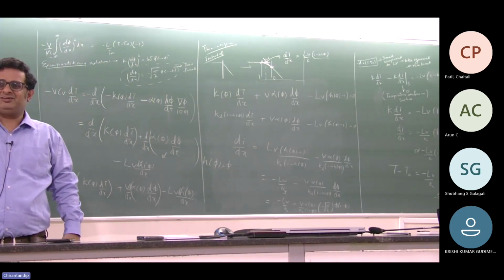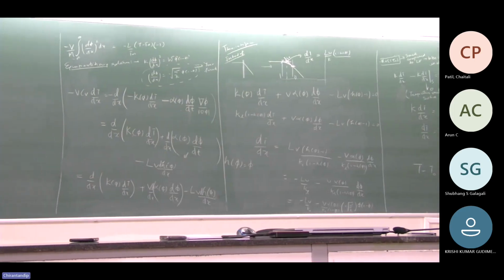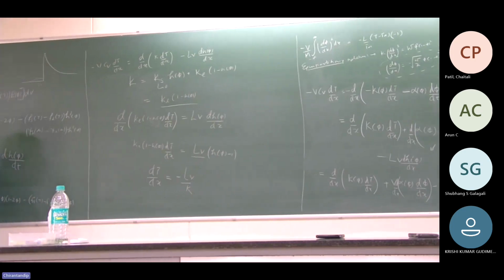But there's nothing called an extra jump. All you have is that this is your typical concentration profile. If the concentration at the interface, CS, is not the equilibrium value but starts to deviate and takes a slightly different value, that's the trapping you are talking about, and then it starts approaching this way.